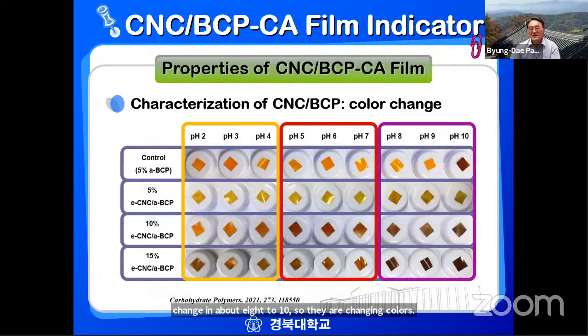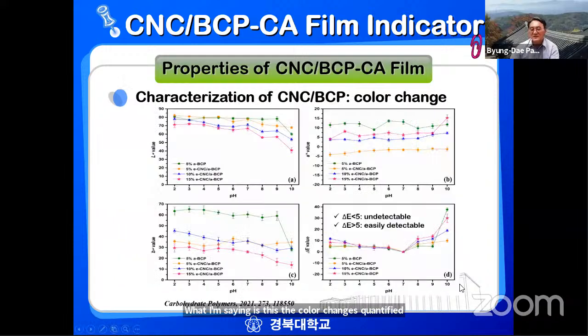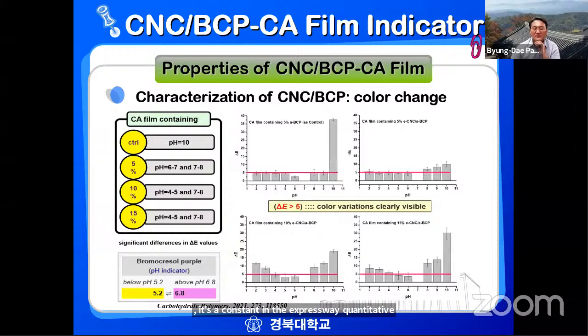What I'm saying is that the color change is expressed by quantitative numbers. And then we used delta E values for different pHs, and here the control is pH 10, and here the control is just 5% activated BCP. Here they only change in delta E value, a dramatic change between pH 9 and 10. But here at 5%, 10%, 15%: 5% shows not much change, but there's a slight change between 7 and 8. That means with 5% composite material in the cellulose acetate film, we can detect the color change between pH 7 and pH 8.